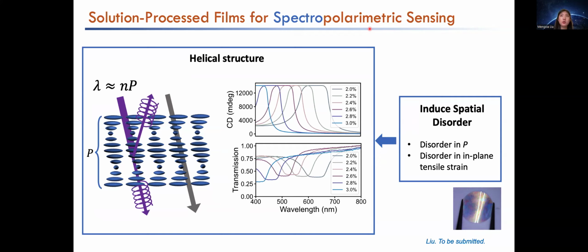Perovskite does not allow us to do that, so we try to look for some new materials. And here, one type is called a helical structure. If we make the material into a helical pattern, it has a periodicity. And by tuning this periodicity, the wavelengths can be tuned. Because this helical structure naturally has a differential absorption of circularly polarized light, it can reflect half of the circularly polarized light when the helicity matches or mismatches the helicity of the original structure. So we observe a very strong differential absorption in the circularly polarized light. But how can we generate the linear dichroism, and how can we further broaden this transmission?